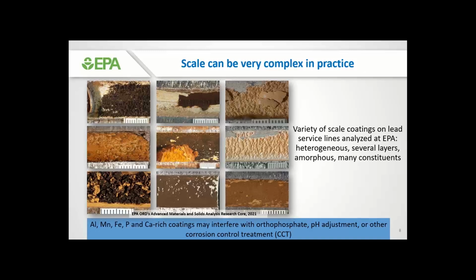In some cases, we may even have other constituents on the scale, not just lead. Those could be anything from aluminum, manganese, iron, phosphorus, and calcium. And if we have coatings like that, which are thick, they may actually interfere with the orthophosphate chemical that we want to add for corrosion control.